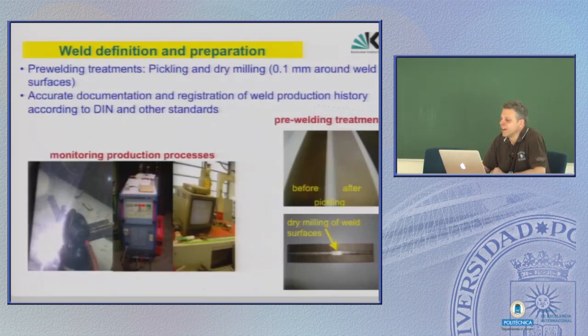First step always is preparation. You can do this on the large scale in the industry. It's done by pickling, by using acid to remove oxides or whatever. We tried this with Eurofer, used such standard acids or pickling treatments, and the result was, as is often the case with Eurofer, not as expected. It produced not a good surface. It doesn't work. I don't know why, but with this 9 chromium steel, at least our trial was completely unsuccessful.